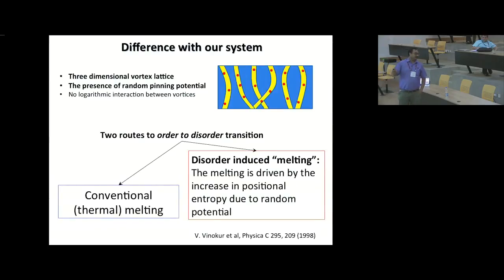However, this is not really applicable in our system. It cannot be, first of all, because I have told you that this is a three-dimensional vortex lattice. Secondly, we have a random pinning potential, which is not what BKT considers. BKT considers a clean 2D system. And the third important aspect, which is more technical, is that here we don't have logarithmic interaction between vortices, at least at large distances. You have logarithmic interaction at very small distances.